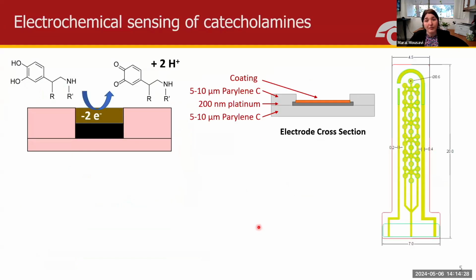Right. So we'll first be talking about the catecholamine sensing module. We're using electrochemical oxidation of catecholamines. There is no antibody or other capture probes on these electrodes. We're using specifically the electrochemical properties of the catecholamines themselves. So we apply a potential, and that potential causes oxidation of the catecholamines. For catecholamine electrodes, we're working with thin film Parylene, but the leads are all platinum, so about 200 nanometers of platinum. The surface is then modified using different coatings. I'll talk more about what those coatings are.